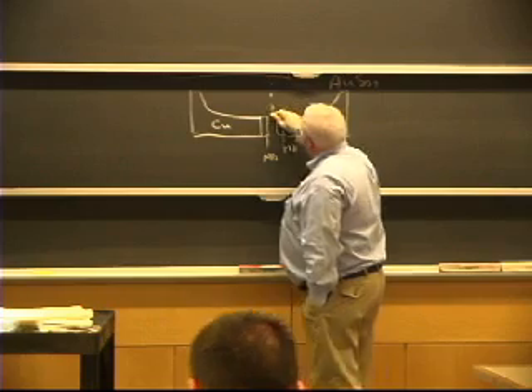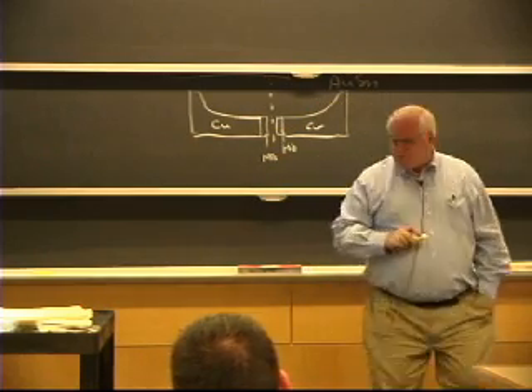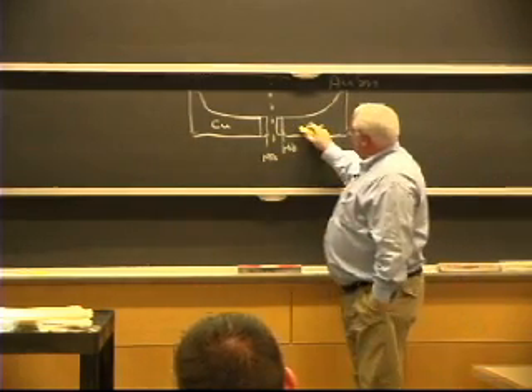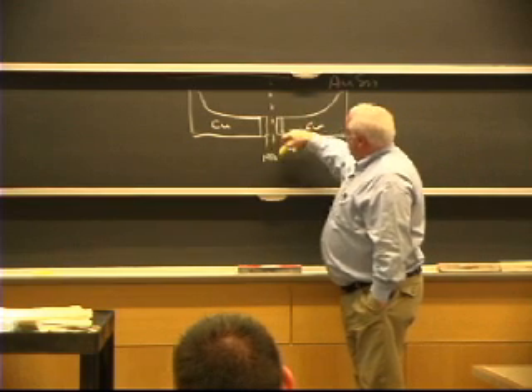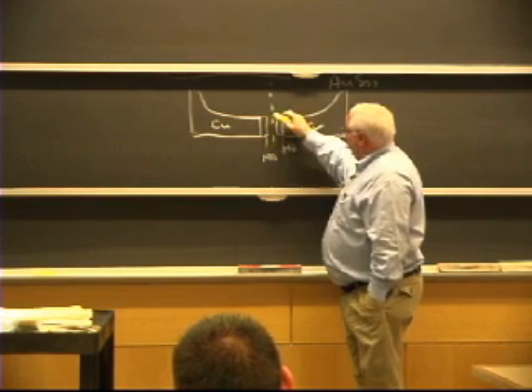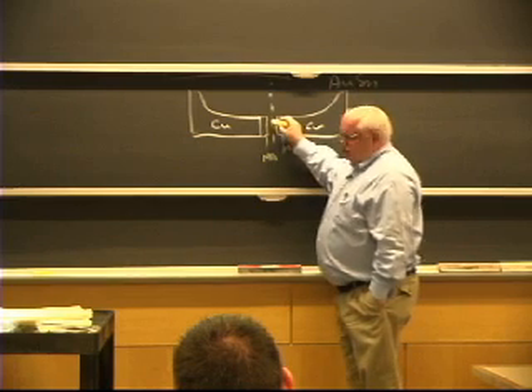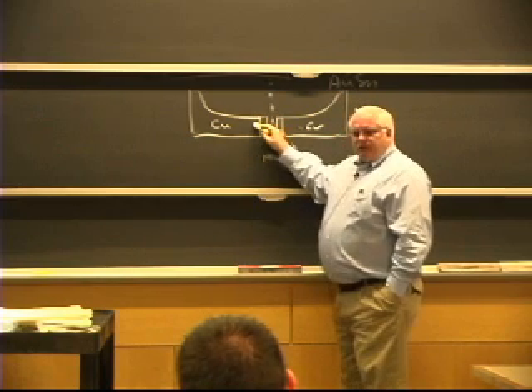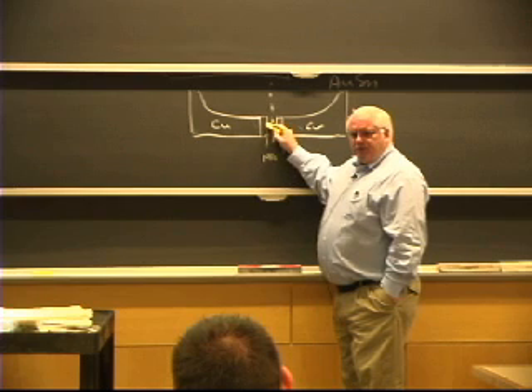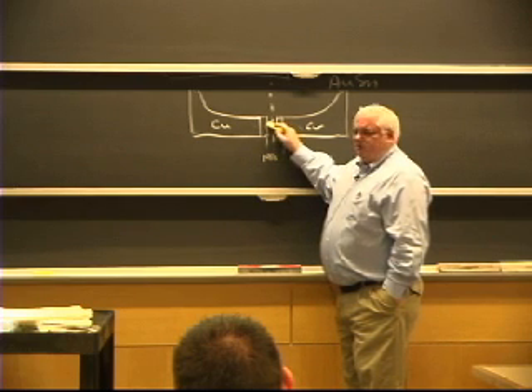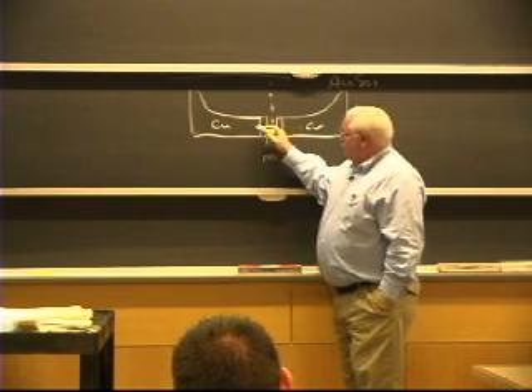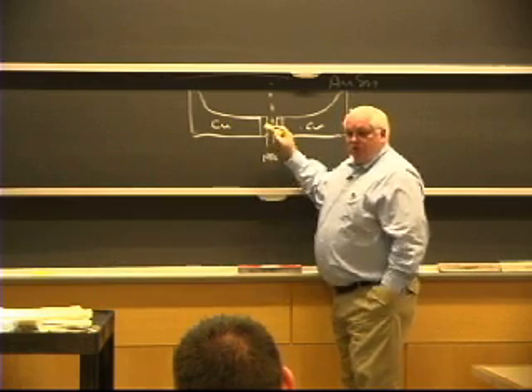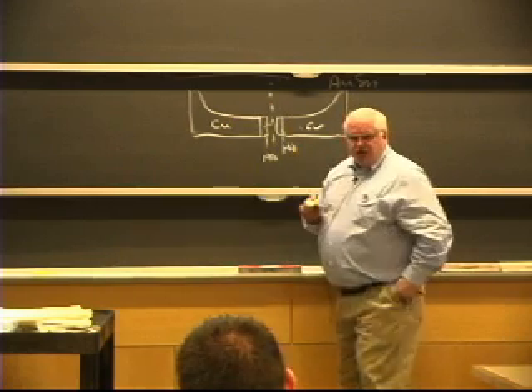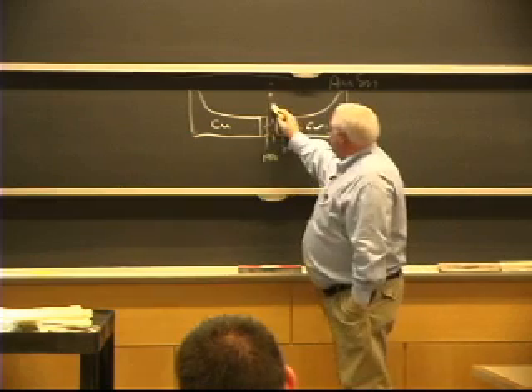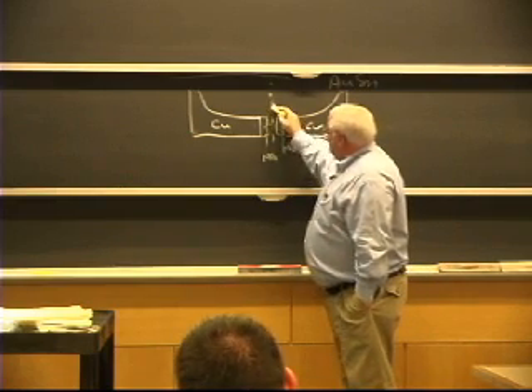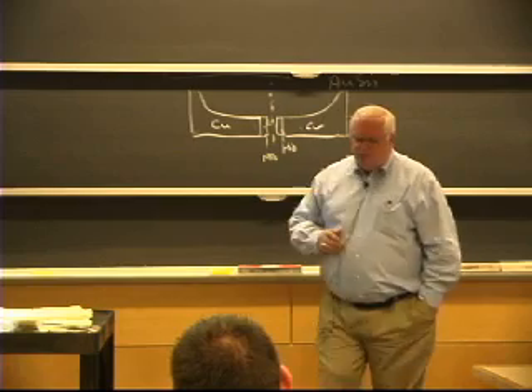And the reason is the electron beam is going to come through this little hole right through the center, and you're going to modulate this with the microwave signal that you got, and you want to magnify it with the electron beam coming through. So you pulse this electron beam through here. There's so much power in the electron beam that it can melt the tips of the copper. So you put something that's very, very refractory, molybdenum, which melts at like 2,500 degrees centigrade. You want copper to carry the heat away, because when you pulse that electron beam, you're going to just kind of flash heat that thing. You don't want it to melt, because if it melts, then you change the electric field around here. And if you change the electric field, you're not going to get the right thing amplified.